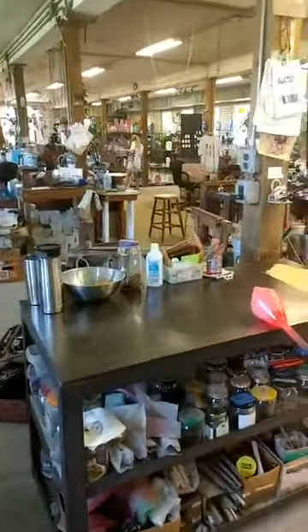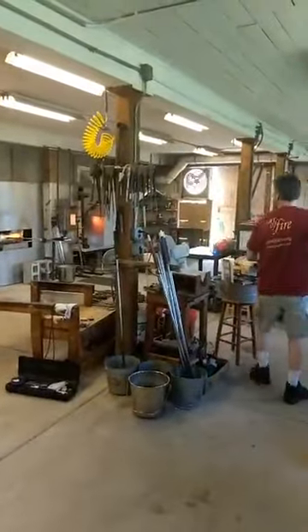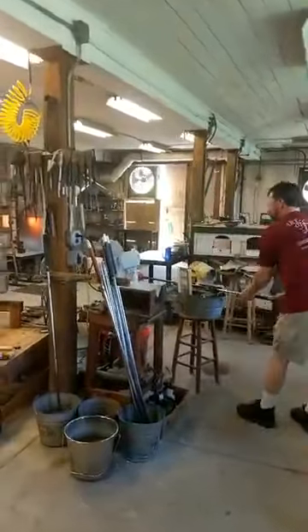When the iron is held down like that, with the tip pointing up, notice how the glass comes off the blowing iron. It's becoming more cylindrical. By inverting the angle, it creates that conical shape out toward the end of the piece. And then he can blow, and it will inflate, but it won't inflate excessively at the bottom. See how he's still got the conical shape, and the middle portion of the glass is blowing out. That's because he cooled that bottom a lot, and that's made it so that it really doesn't blow out there.